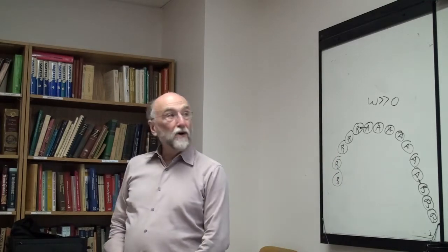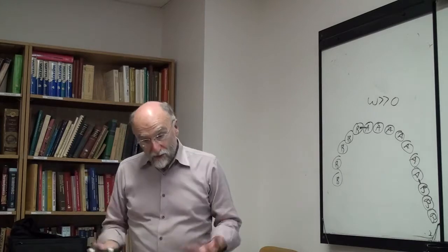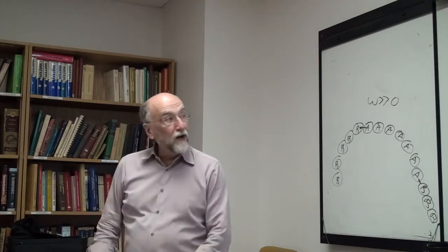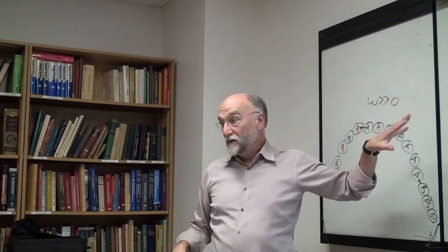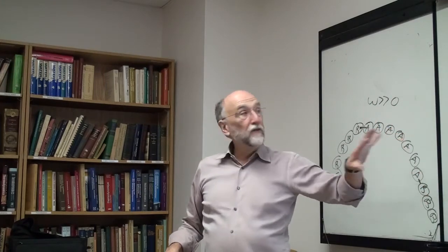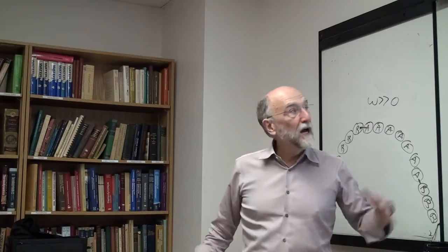In other words, the question was, if we used the real Onsager equation, the proper equation with Z equals 6 or 12 in 3 dimensions, would that then give us a miscibility gap? Or would the quasi-chemical model never give you a miscibility gap if you did it correctly, if you had the proper equation? The answer is, it would give you a miscibility gap.